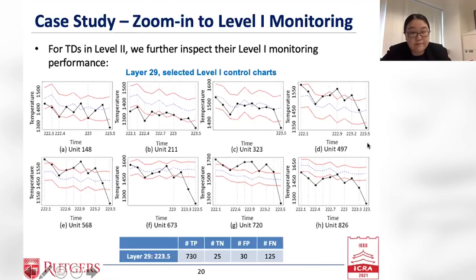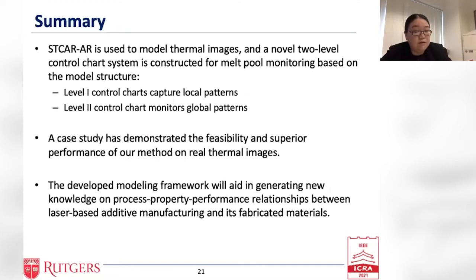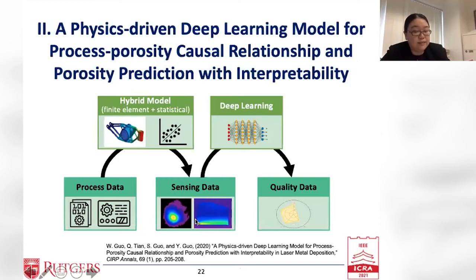A quick summary of this project: we developed a model for the thermal images, and based on the model, we developed a two-level control chart system to monitor melt pool images — one capturing global patterns and the other capturing local patterns. We believe this model is a key element in our proposed digital thread platform because it helps us understand the sensing data and build a model for the melt pool, so we know what a good melt pool image should look like.